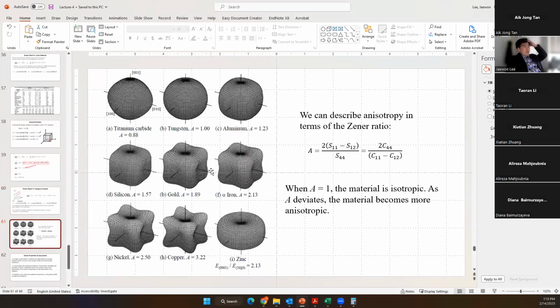And according to the Zener ratio, if it is close to one, it means the crystal structure is almost isotropic. So in case of titanium carbide or tungsten or aluminum, it looks very close to one. It means they have isotropic properties. But if you see nickel, copper, iron, or zinc, they have a very large number for the ratios. It means they have very large anisotropic properties.